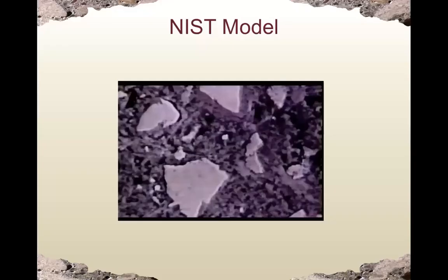As this process repeats again and again, the microstructure develops, building bridges between particles that provide strength to the material. Computer simulation has proved valuable because it allows researchers to test conditions and make measurements that are difficult to achieve in real life. At the end of the hydration simulation, the structure of the hardened cement paste is very similar to that observed under the microscope.